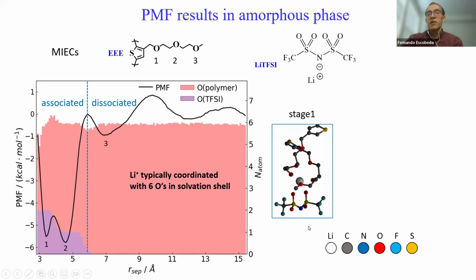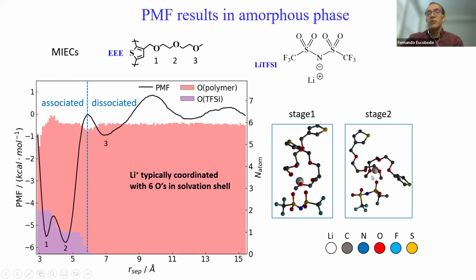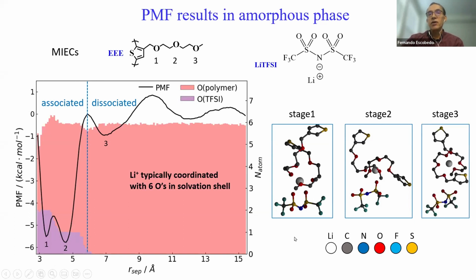And that corresponds to the minimum. So what happens in minimum 2 is when you break off one of those 2 oxygen coordinations with the anion. So now you have this structure. And then when you break off completely this association with the 2 oxygens and the anion, then you have this state 3. So clearly to go from one to the other, you have to go through these little barriers, right? That at the end amount to the total barrier to dissociation. So the main barrier is the one between state 2 and 3. And after that, we will have these other features in the PMF corresponding to basically changes in the solvation environment.